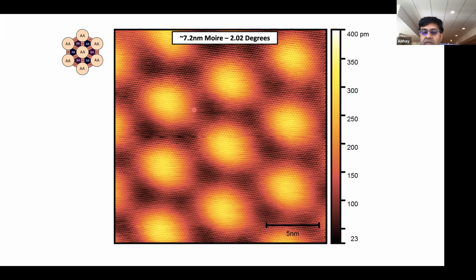So here is a typical example. This is twisted bilayer graphene. You can see the little dots of the individual graphene lattices, and this large superstructure that you see is the Moiré pattern. In this case, this Moiré pattern is 7 nanometers, which corresponds to a twist angle of about 2 degrees. I just want to make the point that the ratio between this Moiré pattern, which is 7 nanometers, and the lattice constant of graphene, which is 1/4 of a nanometer, is quite large. And so what this means is you need a very small number of electrons in real space to fill one of these bands completely. It's very easy to do.